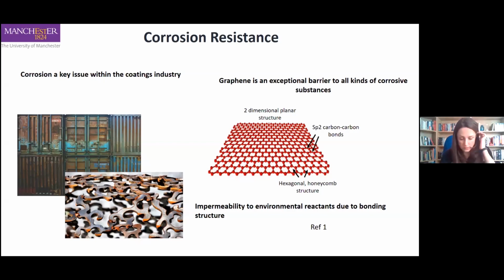One of the reasons to look for alternative materials is because there are so many restrictions now, certainly in the metal protection coating industry, around certain transition metal use. Chromium is the obvious one because of its toxicity issues. So these additives, the constituents, are very restricted now, and you have to use them at very low levels. Graphene's attractive in that sense because it is just carbon, so it's a potential environmentally friendly substitute for other hazardous materials.